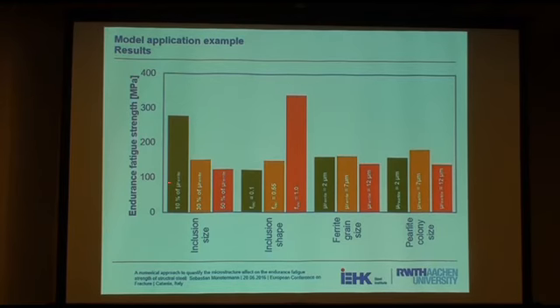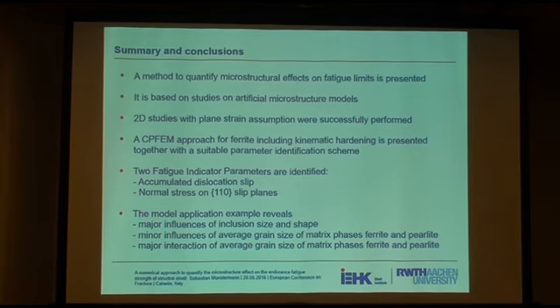You can see, and this is not a surprise, that the inclusion size plays a very important role. Also the inclusion shape plays a very important role, but you can also see that there are some minor contributions coming from other microstructure parameters. The most important ones are listed in here, so it's mainly also the relationship between the ferritic and the pearlitic grain size.